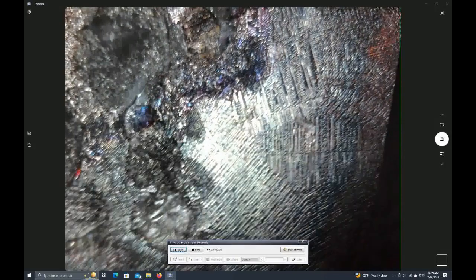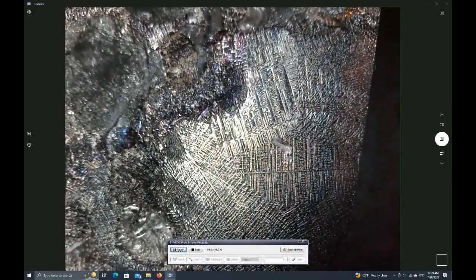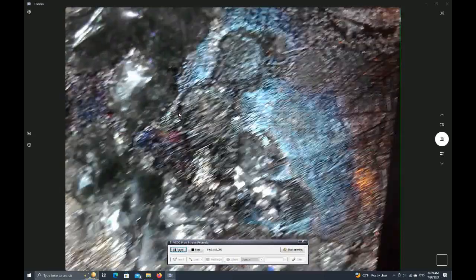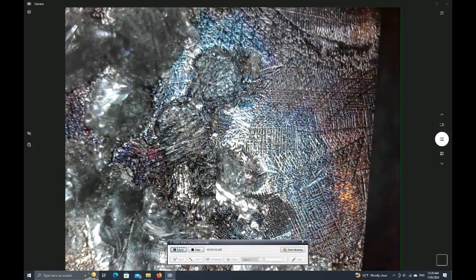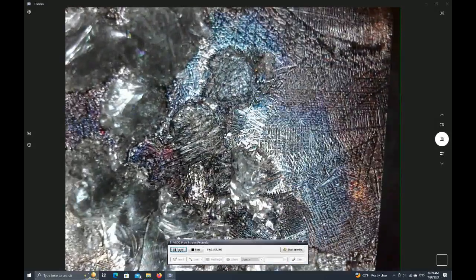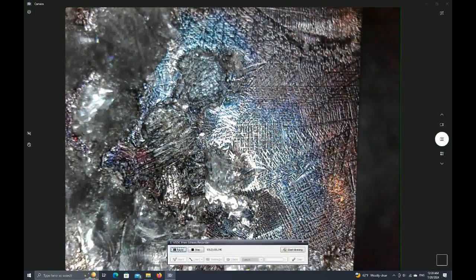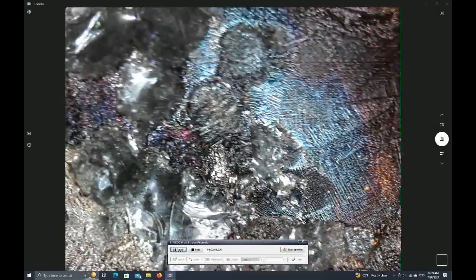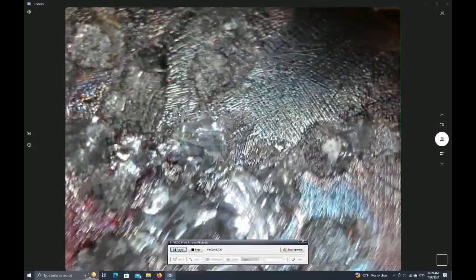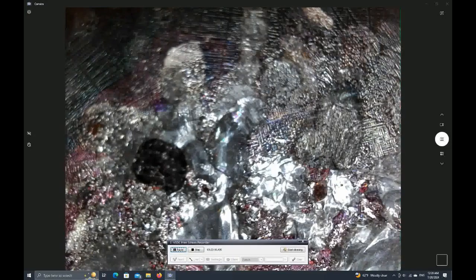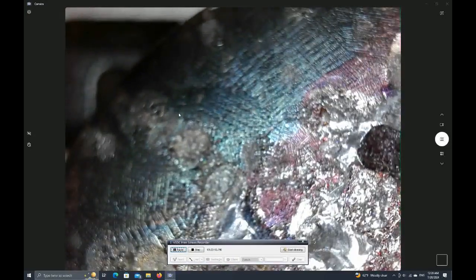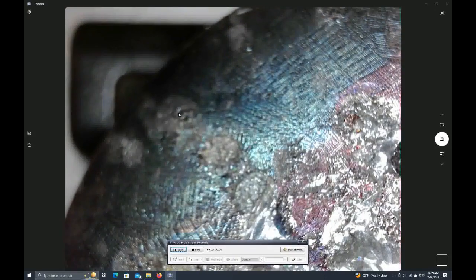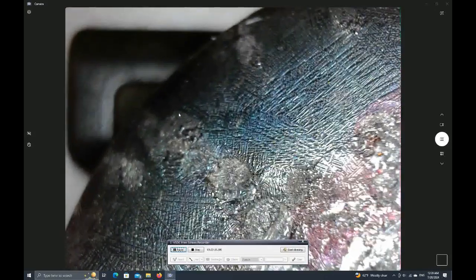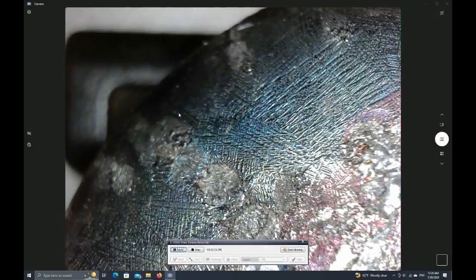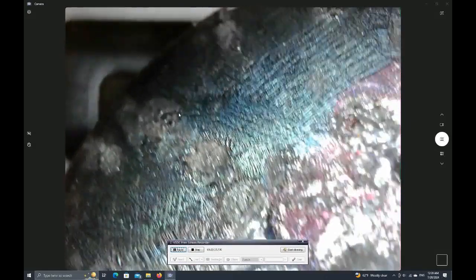I do not think I've ever had this beautiful of dendrite formation on a crucible ingot since I have been on this campaign. And you see the sharp wall here. It's not round because that's the area that we ground away for etching. But I have never seen this thorough coverage of dendrite formation on the periphery of a crucible in this whole campaign. I've seen some good stuff, but not like this. So I really think the combination of glass inside the crucible and sealing the crucible with Satanite refractory is definitely the way to go, because these results seem to be quite a bit better than what I've seen before.